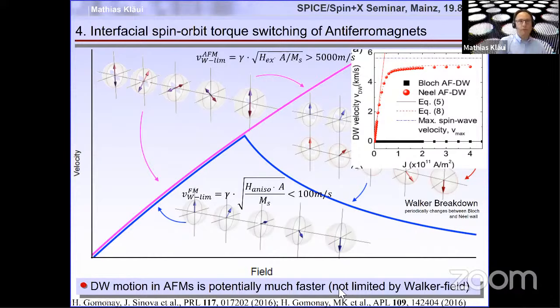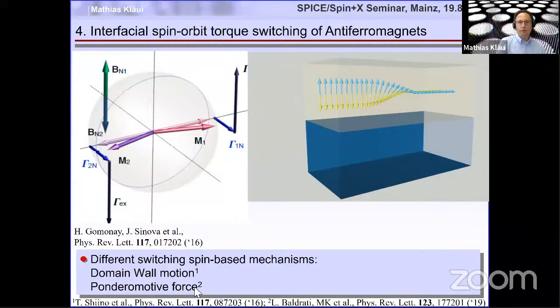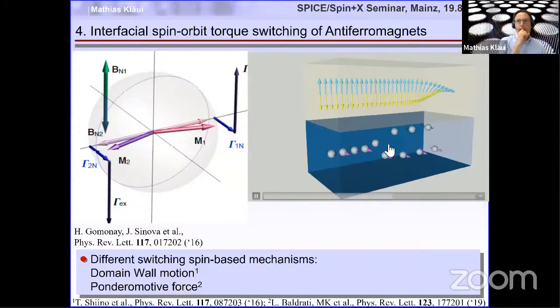So you're not limited by the Walker field, but you also have a problem, because the domain wall motion direction is set by the chirality of the domain wall. So if you don't have a chiral exchange interaction, then some domain walls will move this way, some will move that way, but you don't get net switching. However, there is a second effect, which was predicted by Helen, the so-called ponderomotive force in this paper here, where you actually get a 90 degree reorientation of the Néel vector due to the injected spins. And this 90 degree reorientation then gives you a net switching due to this ponderomotive force.